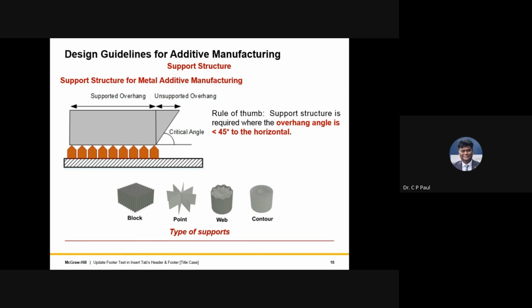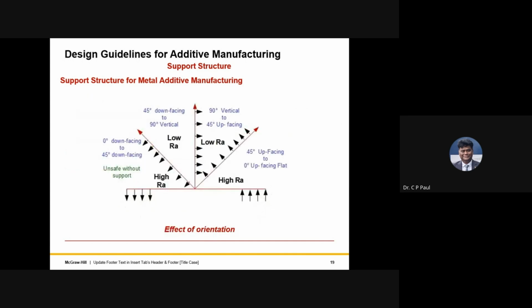In general, support structure is required when the overhang angle, the critical angle that I am talking of, is less than 45 degree. If it is more than 45 degree, mostly people are able to manage without building the support structure. Now, if you compare the support structure with the surface roughness, you'll find how the component comes.